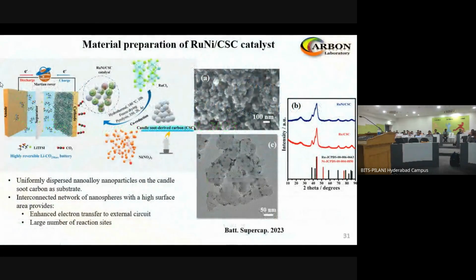And so here again, it's a very simple synthesis process, just like what we have done. We have taken the ruthenium chloride and nickel nitrate salt, and then did the hydrothermal process in the presence of candle soot carbon. Now we have the ruthenium nickel deposited on the candle soot carbon. And this is what we see in the TEM pictures, that these are the ruthenium nickel catalyst, which now has the candle soot particles very nicely dispersed uniformly on these structures.